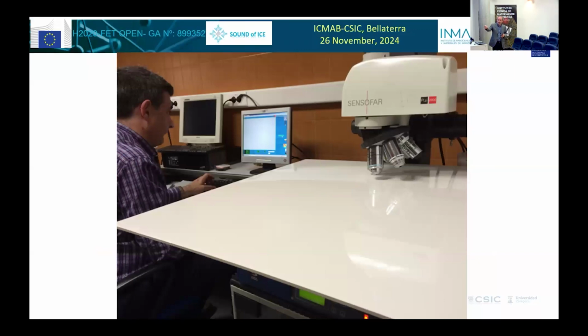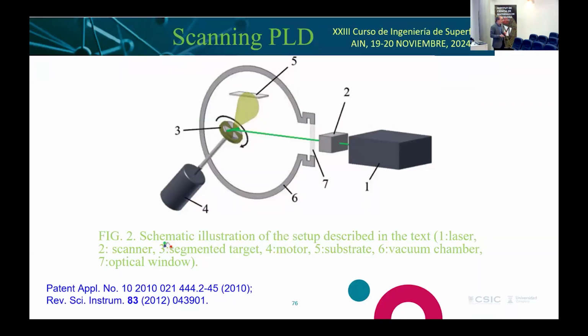And this is the measurement by Professor Angurel, my colleague, who is measuring this 60 by 60 piece on the confocal microscope. You can see the reflection. And this one in particular gives an average roughness value of about 40 nanometers. So this is, I think Florian will like this more because this is a scanning PLD that we patented at the Max Planck Institute with my colleagues Dieter Fischer and Martin Jansen years ago. And in this case, what we do is we scan the laser, so this is a scalable PLD. You can do it in large areas and continuous. So this is very interesting.